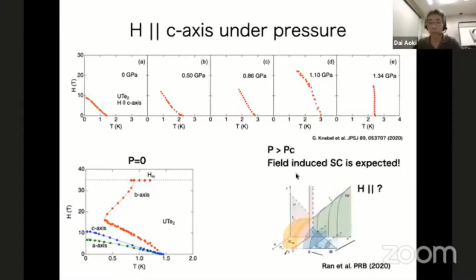And Shen Ran's group showed this kind of phase diagram schematic. In their paper the field direction is not clear, but I expect that for the C-axis, applying the magnetic field just above the critical pressure, there is real field-induced superconductivity. I mean, at zero field there is no superconductivity, but under magnetic field it shows superconductivity. This is a very strange case.